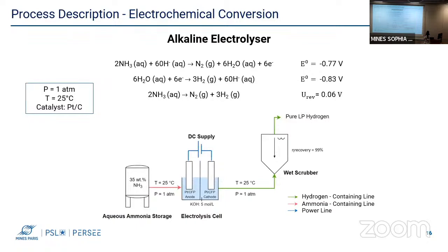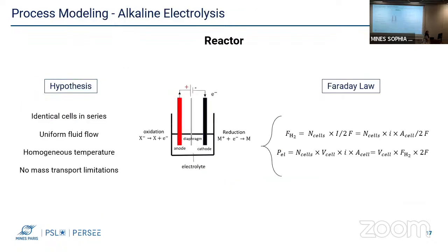As for the electrochemical route, aqueous ammonia solution is introduced into the electrolysis stack. This stack operates at a temperature of 25 degrees C, pressure of 1 atmosphere, in the presence of platinum-based electrodes and a highly concentrated alkaline electrolyte. The effluent of the stack is sent into a purification unit in order to recover pure hydrogen. This stack is modeled as a group of identical cells connected in series with uniform fluid flow and homogeneous temperature, while neglecting mass transport limitations. The model was developed based on the Faraday law.